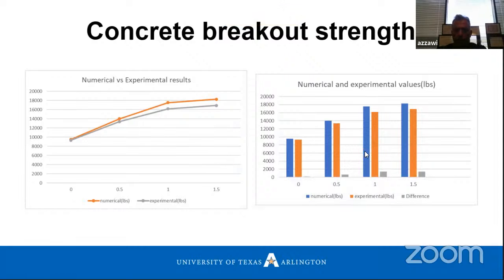Okay, this is another chart. We did some parametric study to change the diameter of the anchor bolt and keep the embedded length the same. We noticed there's not much difference, honestly, if we increase the diameter of the anchor bolt. If we increase it from 0.5 to 0.75, as we see, there is not much difference in the strength. And the reason behind that is that the concrete breakout usually depends on the embedded length, sorry, not on the diameter of the bolt. It has an effect, but this effect is not too much.